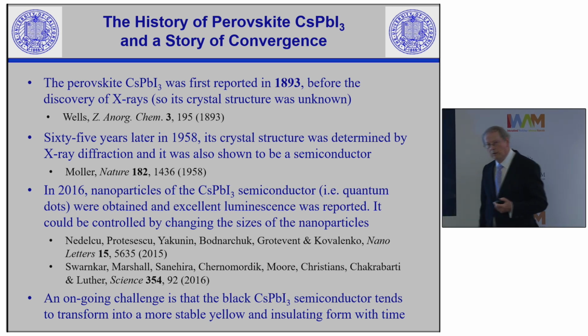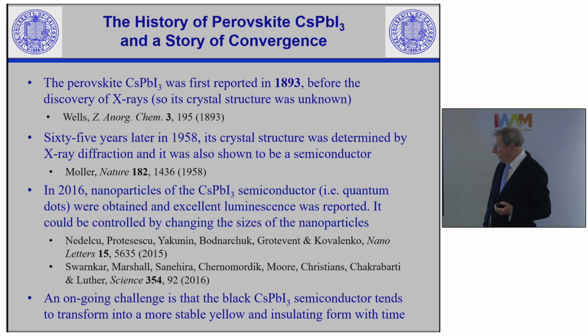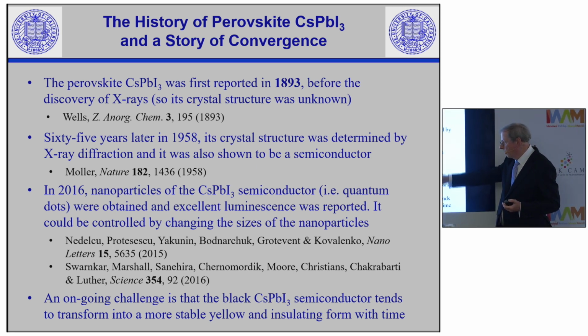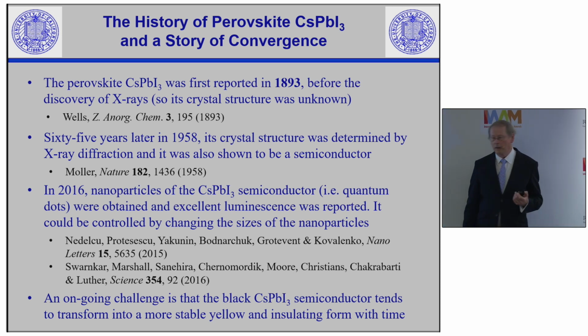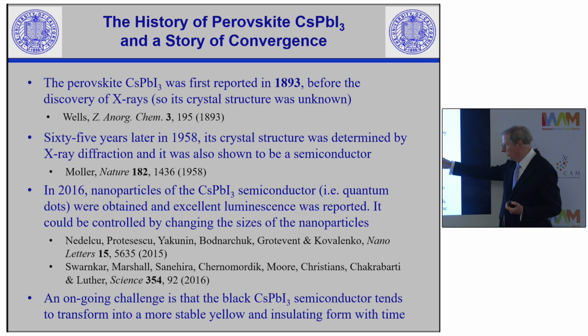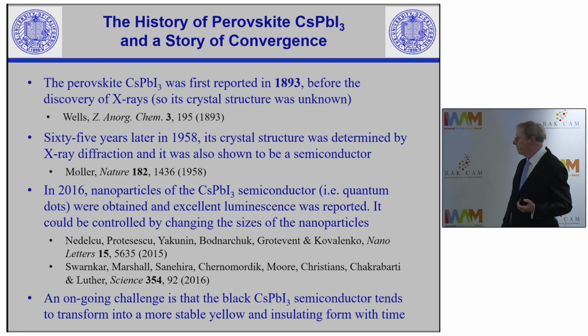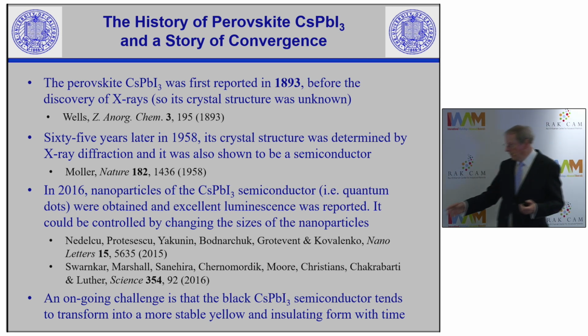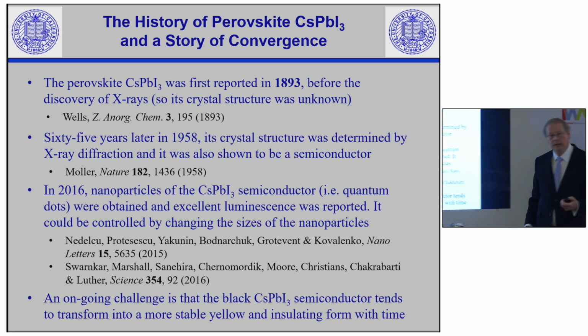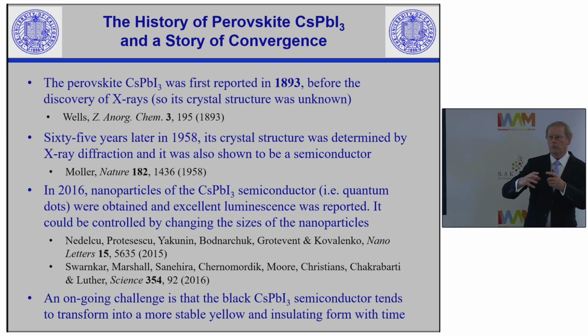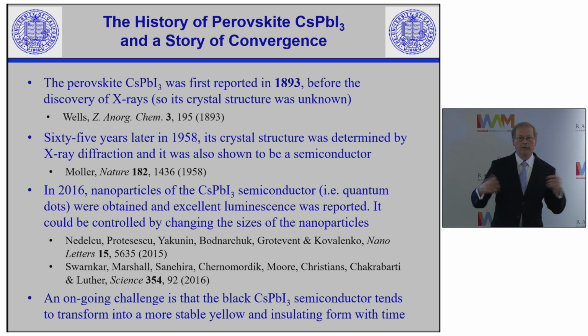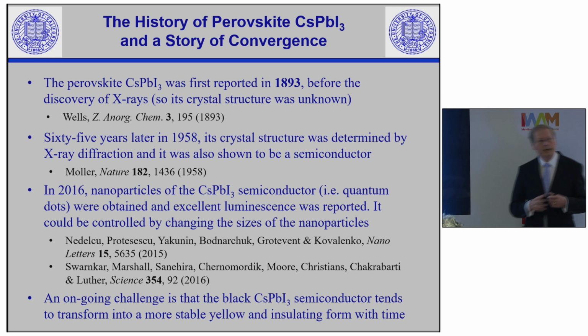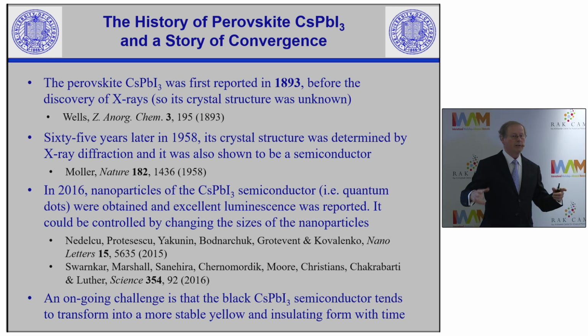But this one didn't look to be particularly important until people found that you could make quantum dots out of it, like the quantum dots I was showing you earlier. High performance quantum dots for optoelectronic applications. The problem is that cesium lead iodide has 3 different forms, and only one of them is of any value because it's semiconducting. The other ones are yellow, and they're not semiconducting and they're useless. And so at room temperature, the yellow forms a stable one. And so you need to be able to stabilize the high temperature form.